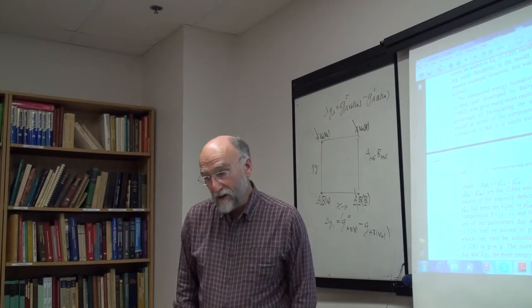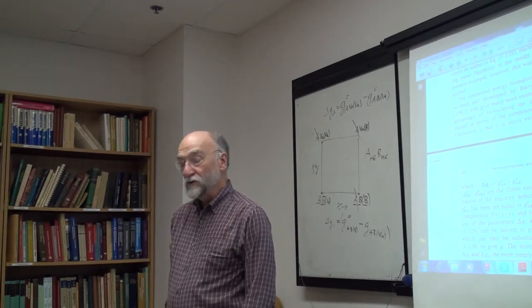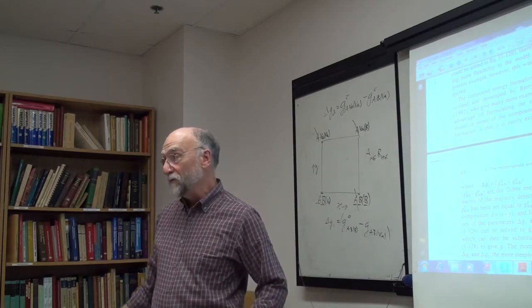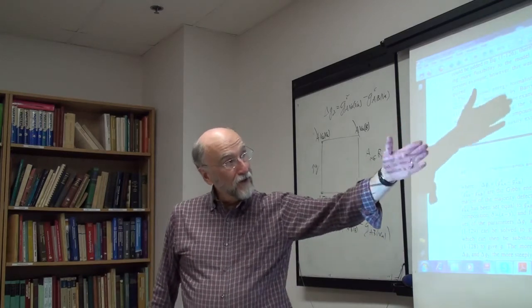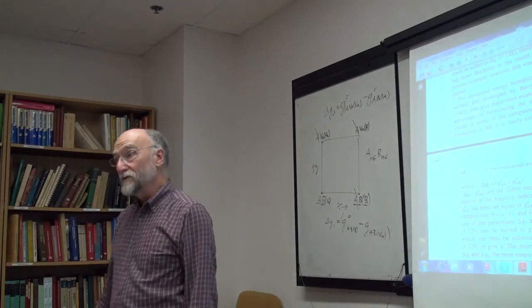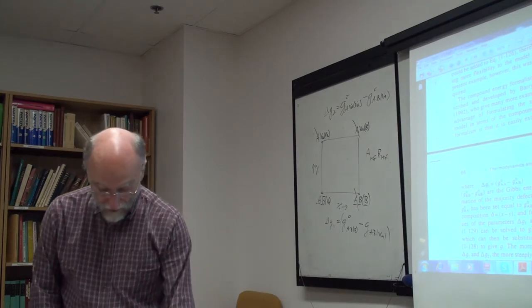Going back to the associate model versus the quasi-chemical model: the associate model fits nicely because the equations in the binary look the same, but when you go into the ternary, the equations don't look the same. The same thing can kind of happen here. So you can get a nice fit to the binary with any defect model, but it won't necessarily be the case in the ternary system.